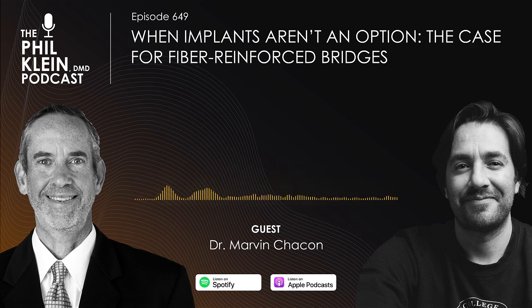You have the longitudinal fibers that go across in the direction of the arch. It follows the arch, but then you have a short one that goes 90 degrees to it. Am I correct? Yeah, this is the oblique one. And this fiber, the literature mentioned or showed, helps to absorb lateral forces and avoid the fracture of the veneering materials in posterior bridges.